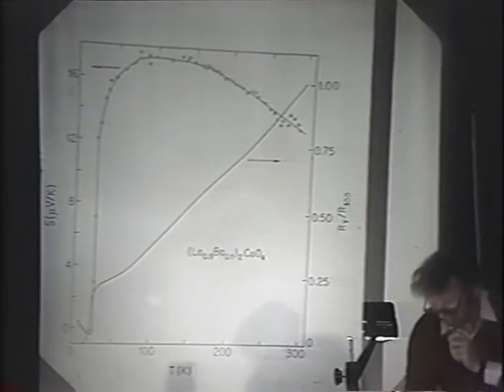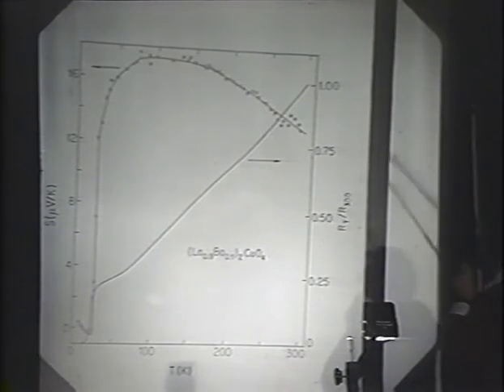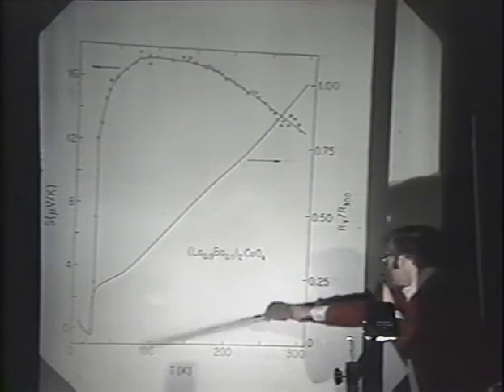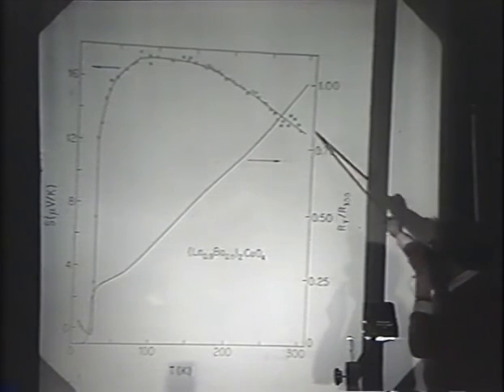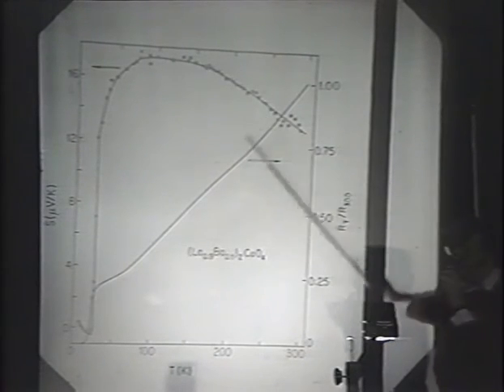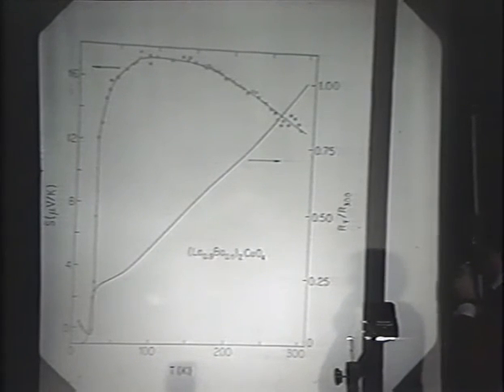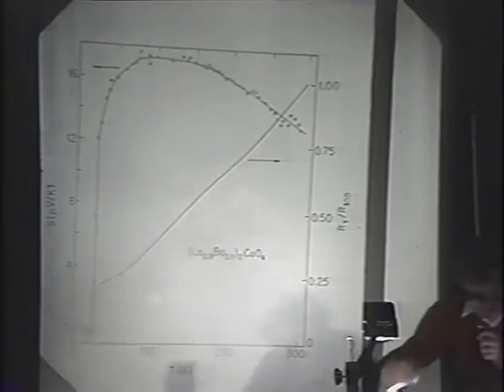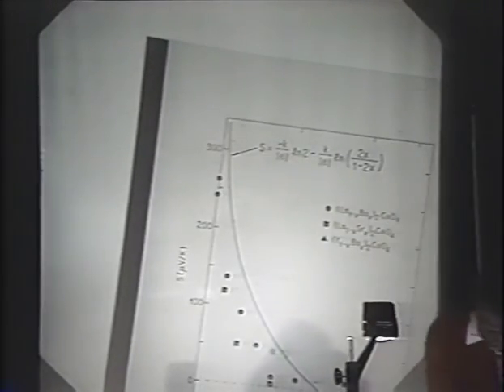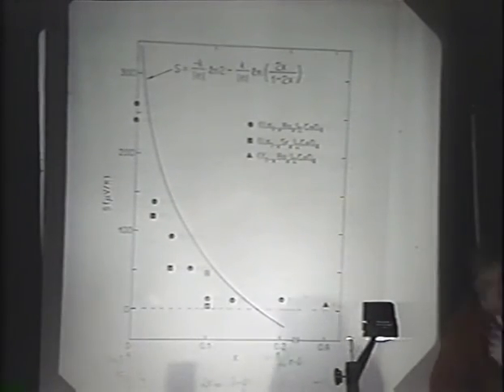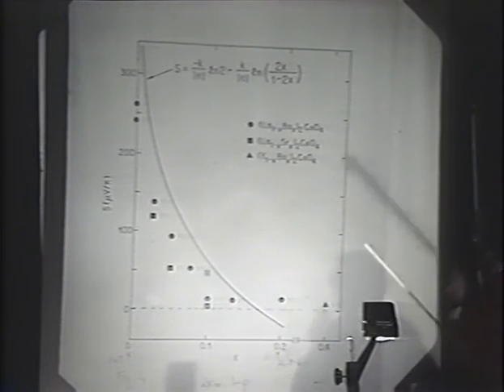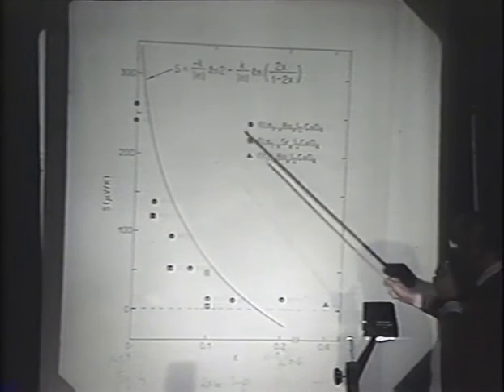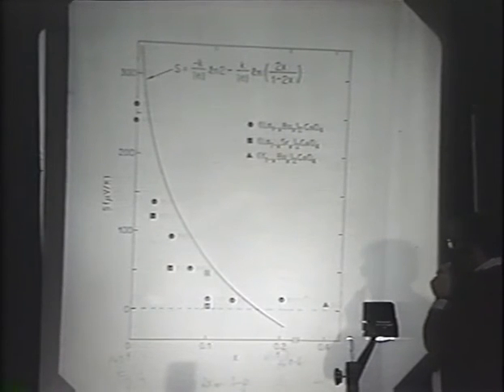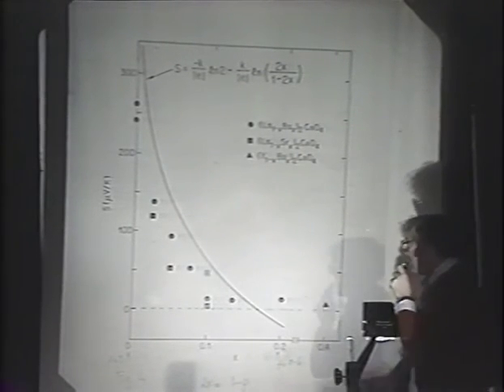You've seen many this evening of thermopower versus temperature in the superconducting region. This is resistivity versus temperature. And you've got a large positive, not very temperature-dependent thermopower in this so-called metallic state. So I'm jumping transparencies. This shows every thermopower sample that we've measured at UCLA. I didn't leave any points off. I added this one so that I could say this.